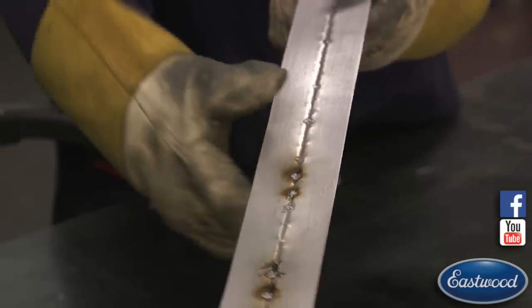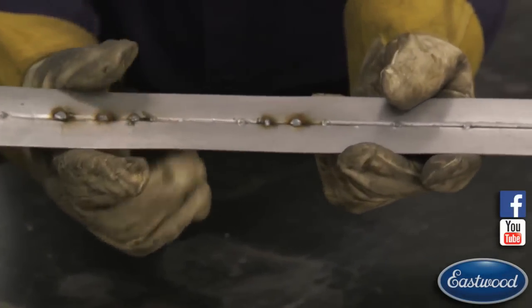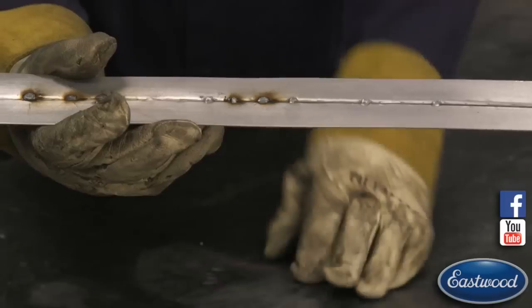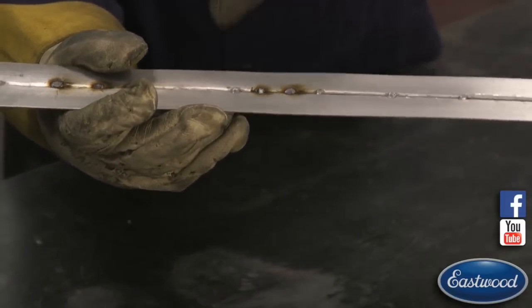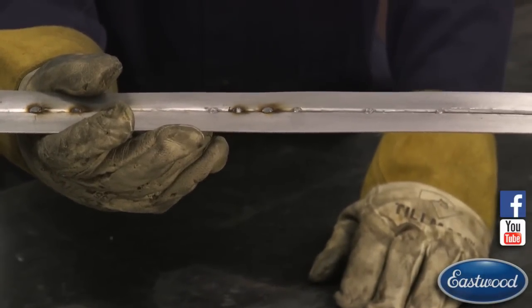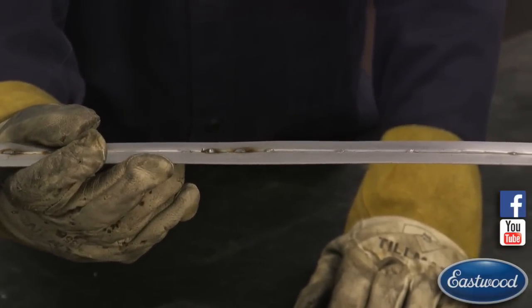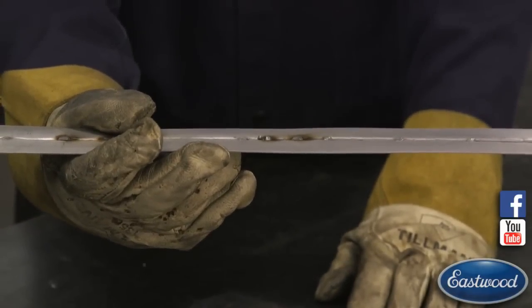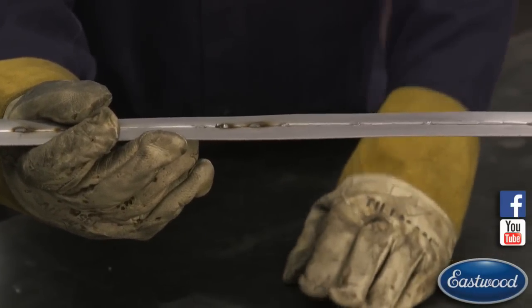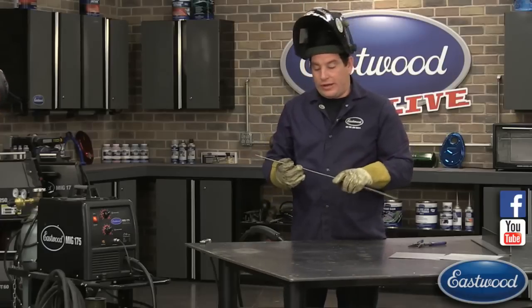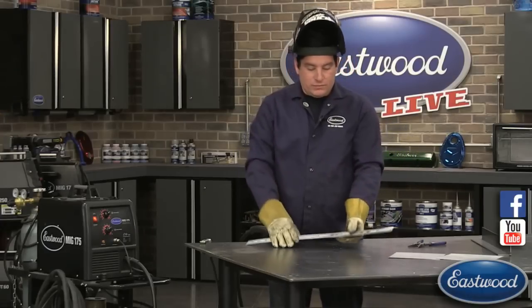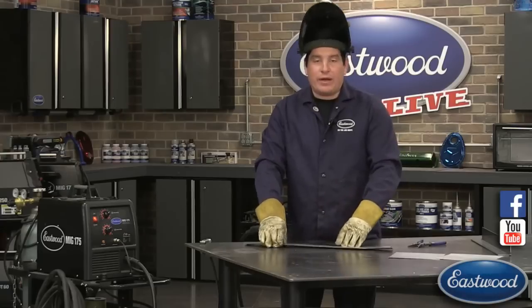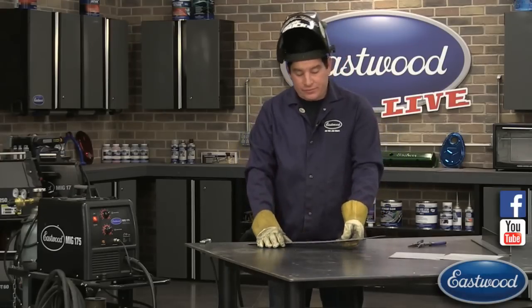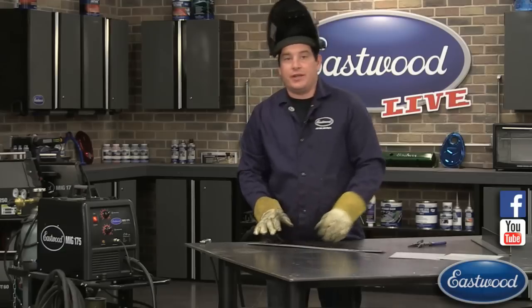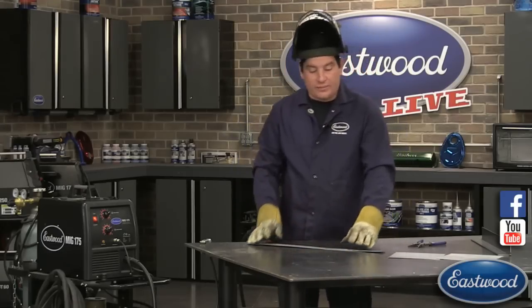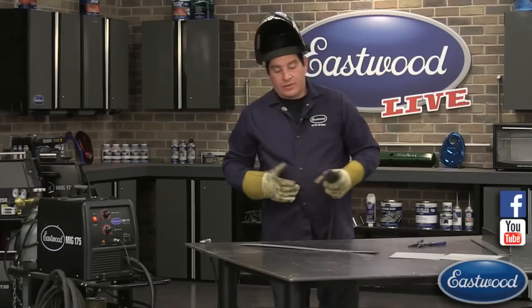So you can see this one. Let me turn it sideways so you can see it a little better. This first one here is where it was further away. You can see how it's up over the panel, it's up higher, and this other one's pretty much flush. So we're going to have to do a lot more grinding on the first one. All I did was have the wire and my hand a little further away, and it made that big of a difference. That weld's not going to be burned through as nicely, and you're going to have to do a lot more grinding, which puts more heat into the panel, which causes more warping. It's just all around bad. So that's two things to show there.